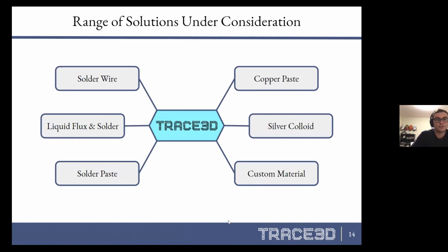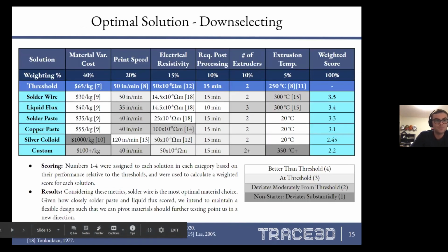With these characteristics in mind, our down selection proceeded between 6 different materials with which to extrude our conductive traces, these being solder wire mixed with liquid flux, solder paste, copper paste, a silver colloid, and a custom material. So we found values for each of these 6 materials across those 6 quantitative stakeholder informed characteristics that were previously mentioned. And as shown here, solder wire was the winner.